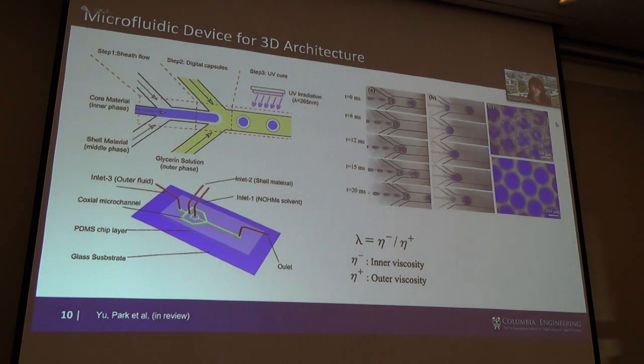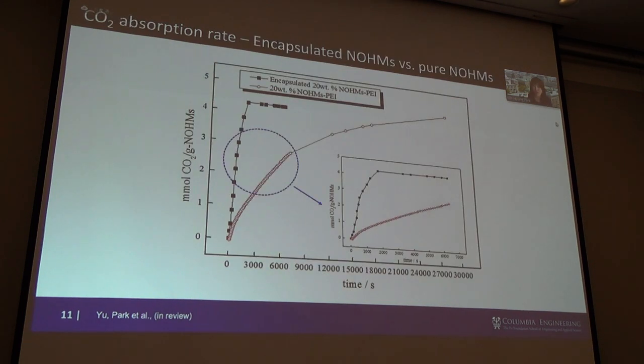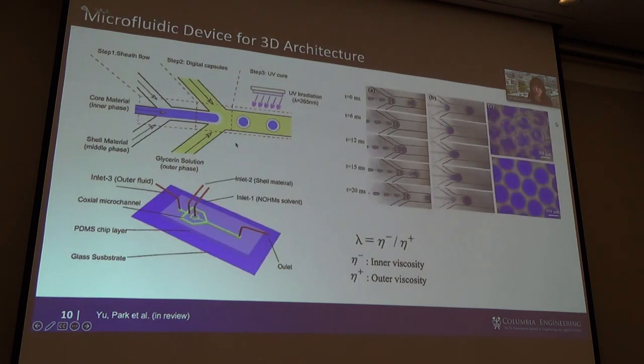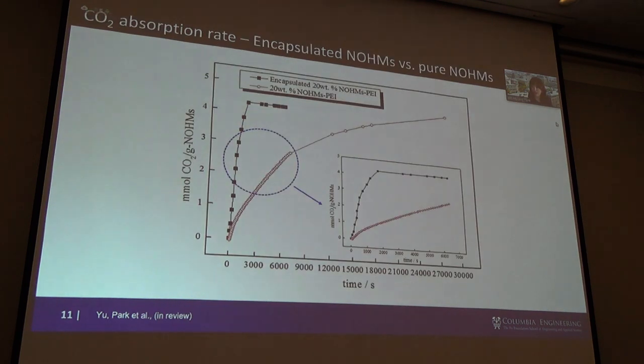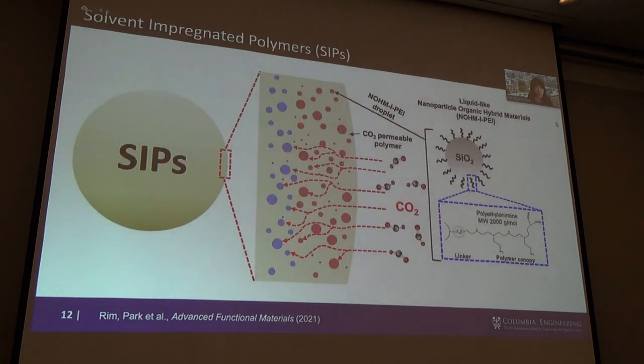So it could be single core or multi-core, and as we expected, all these materials start to capture CO2 much faster, with faster kinetics. But we thought that, well, obviously multi-core works much better because there's more interfacial area. So why can't we push all the way, and can we overcome using a microfluidic device, which is much harder to scale up? So the second generation of encapsulated NOHMs liquid solvents, what we did was this material. We call this a solvent impregnated polymer.